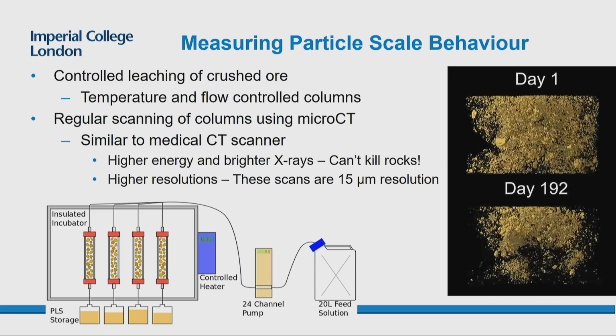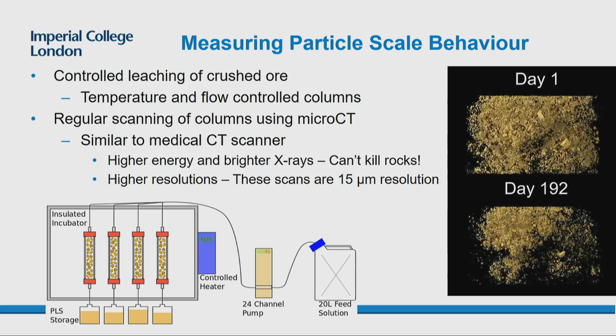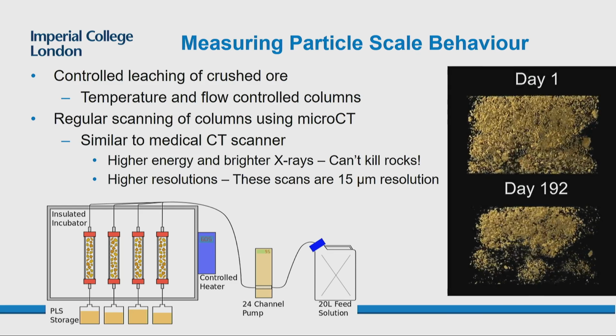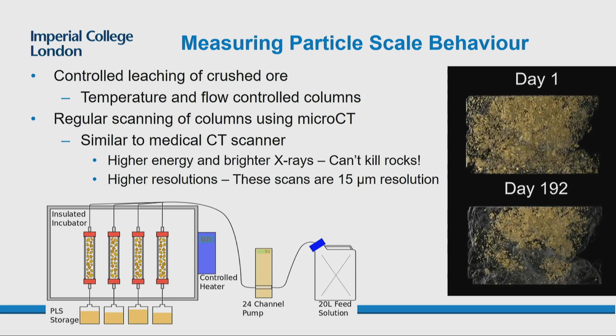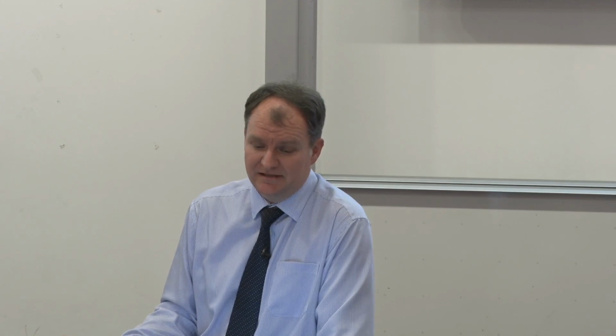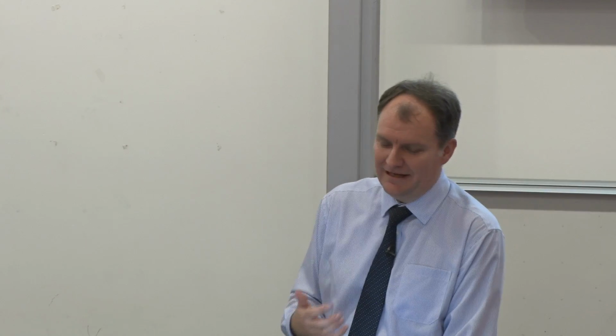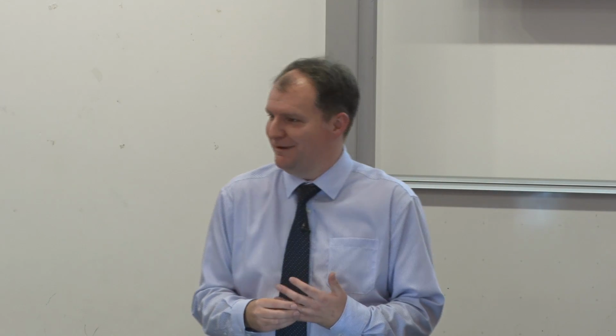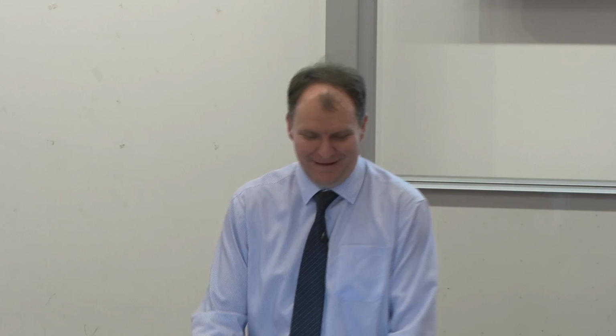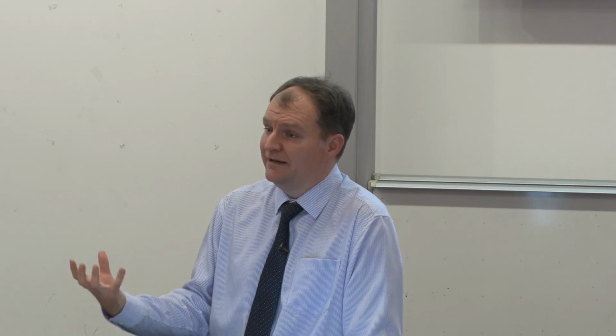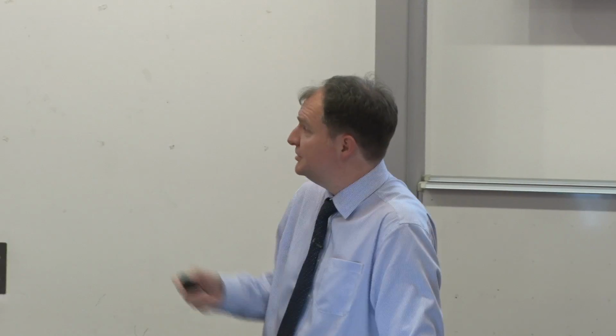So we were scanning them to start with every day, then every week, then every month, so we could produce this whole set of images of the rocks, and these were done using micro-CT, so very similar to your conventional medical CT scanner, except you can use much higher energy and much brighter X-rays than you can in those because you haven't got a patient to kill. It doesn't matter what you put into the rocks. And because of these higher energies and much smaller samples, we get about 15 micron resolution. So we can look in quite some detail at what's going on in there.